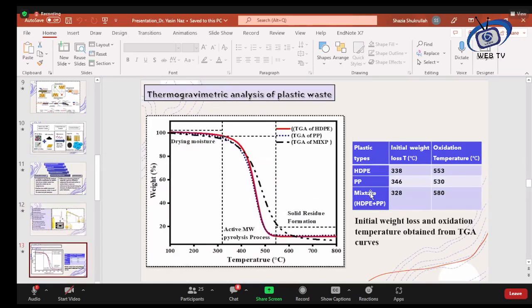Okay, the important thing before we start this process is to know in what temperature range the plastic can be effectively converted into valuable products. For that, we conducted thermogravimetric analysis and checked the initial temperature and oxidation temperature of the plastics. We observed that in thermogravimetric analysis, the initial degradation of the material, or the weight loss, starts at about 300 degrees Celsius, and the oxidation temperature starts roughly around 500 to 600 degrees Celsius. It means the pyrolysis, or the deconstruction of the plastic, should be done between 300 to 600 degrees centigrade for effective conversion of the plastic into valuable products and the residue.